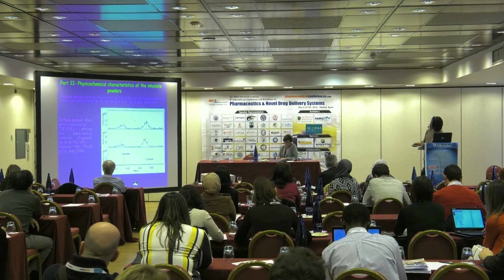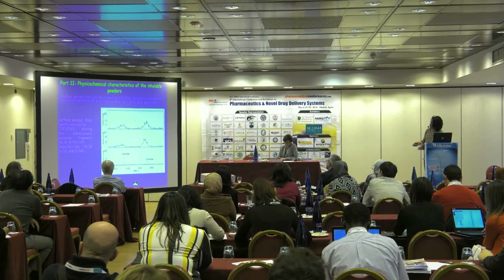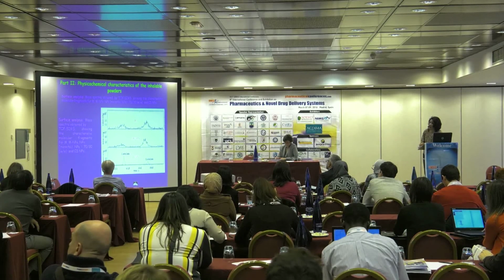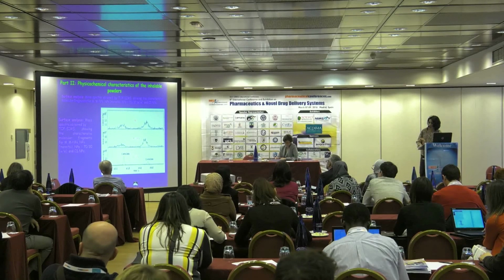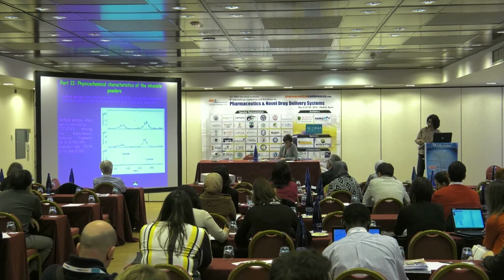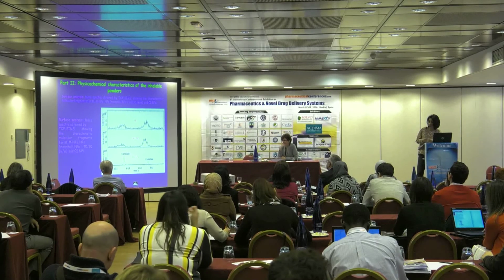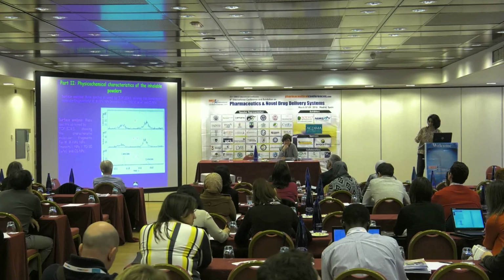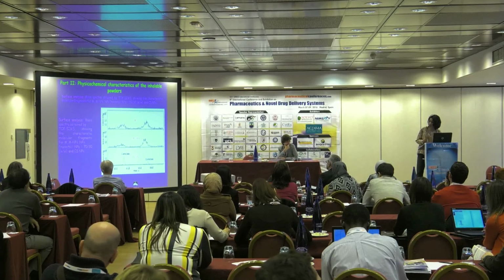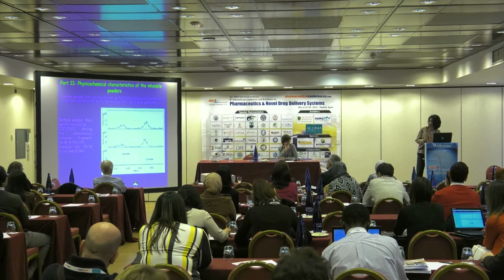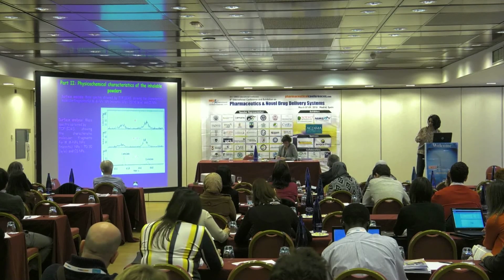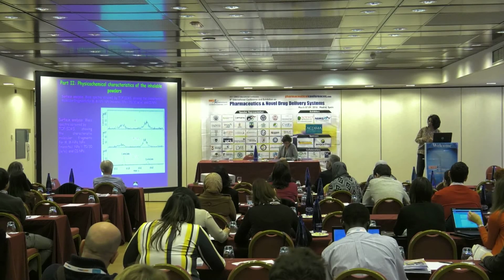For example, these fragments contain a sodium species attributed to the cross-linker. This is a further clue that the surface composition of the mannitol microsphere containing the nanoparticles had the same composition, the same elemental elements, and with the same proportions. This strengthens our assumption that we only have mannitol on the surface, we don't have nanoparticles there.